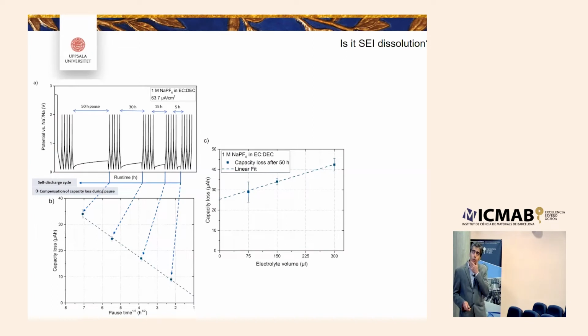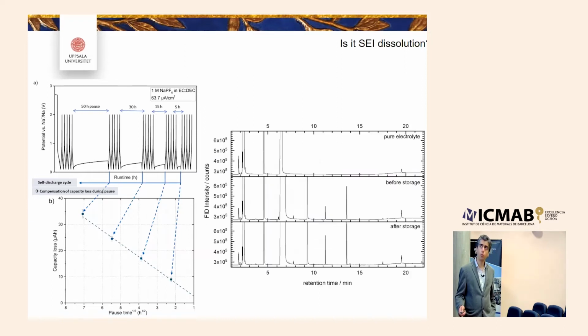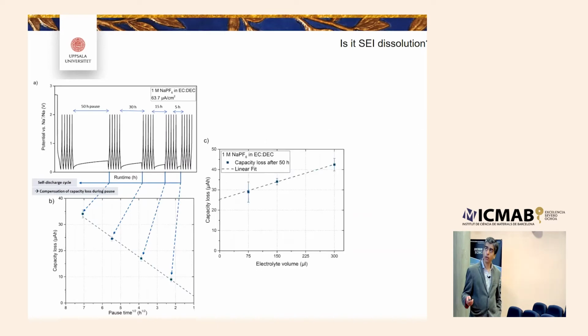So the first test we did, shown on the top left, was galvanostatic cycling of the negative electrode material—a few cycles, then pause, a few cycles, then pause. We tried carbon-based anode materials, high surface area carbon-based material like Super P, but also low surface area metallic gold and platinum. So we worked on model systems, but also on real systems using either low surface area hard carbon or high surface area carbon black.